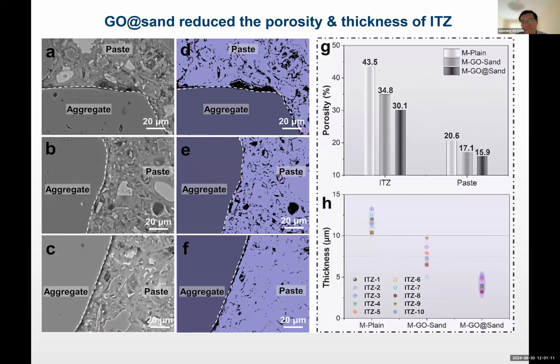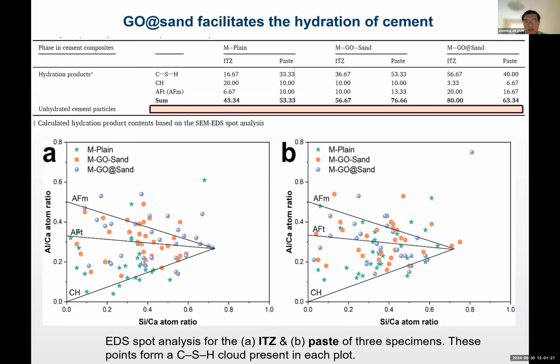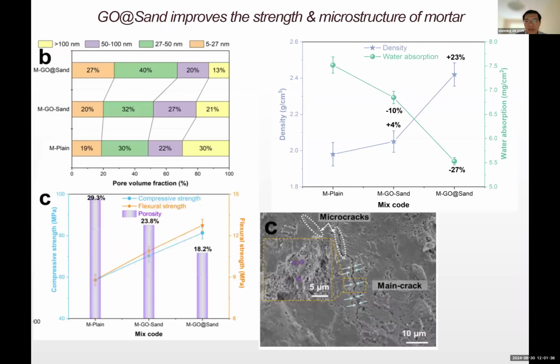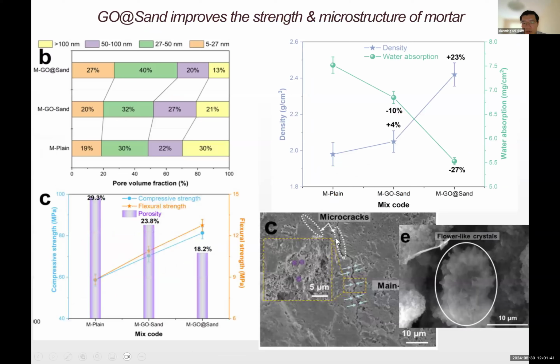And also under scanning electron microscope, we can see that the interfacial transition zone on the surface of the sand, in this case, is actually densified and becomes narrower. And we understand, this is a nanomaterial, so it actually interacts with the cement paste, and the cement hydrate chemistry changed. There are more details, but one thing I want to point out is that the cracks have become finer, and when it heals itself, this beautiful hydration product forms. I think it's a carbonate.